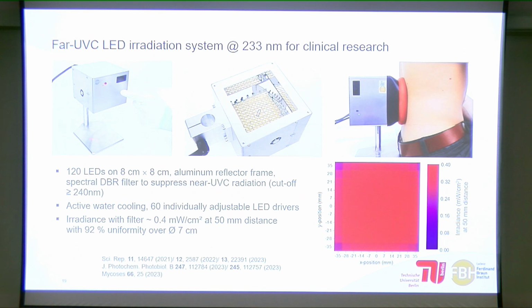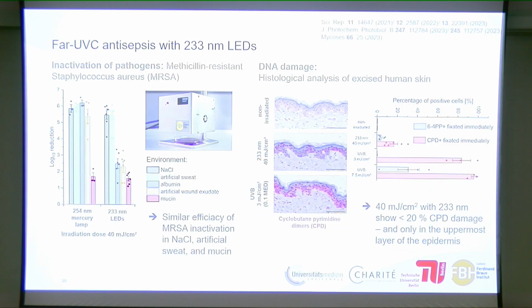And we built such an irradiation system based on 120 LEDs in an 8 times 8 centimeter system, and we use active water cooling. We can also adjust the emission from the individual LEDs so that we get a very homogeneous emission. So we have 92% uniformity over 7 centimeter diameter. These systems were then used with the Charité and with University Medicine Greifswald to do some tests on MRSA, where we could show that we could inactivate MRSA with the 233 nanometer LEDs without causing any significant damage. More information on these tests will be shown tomorrow at Martina Meinger's presentation.